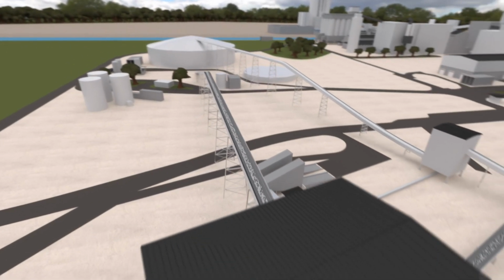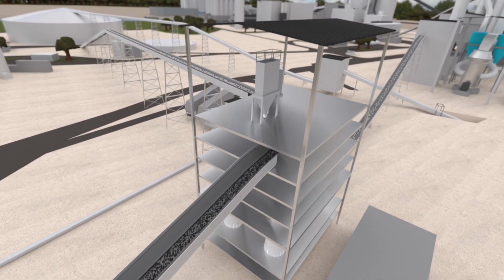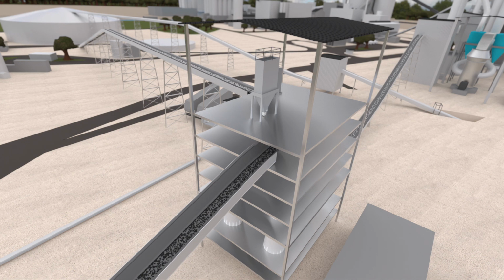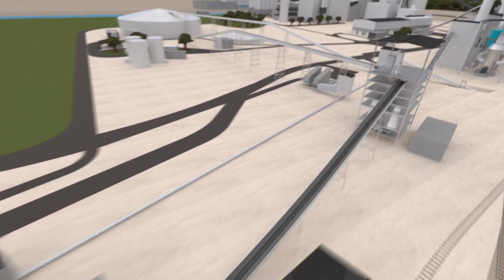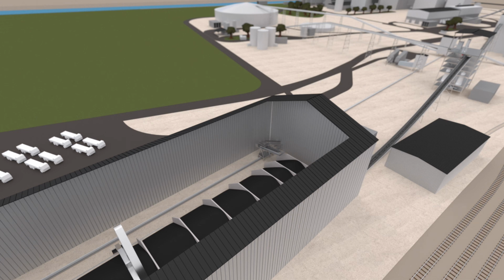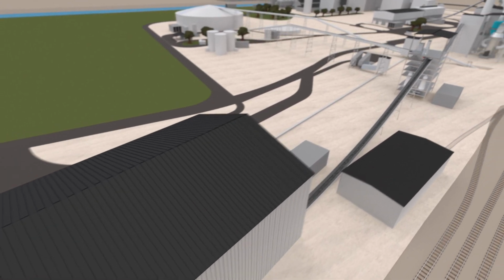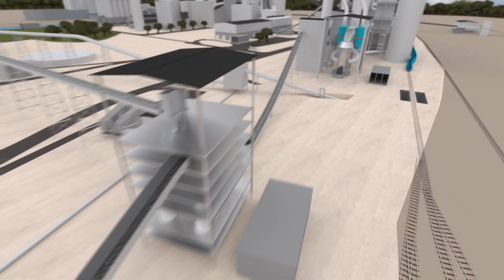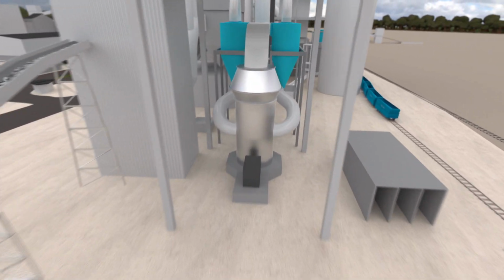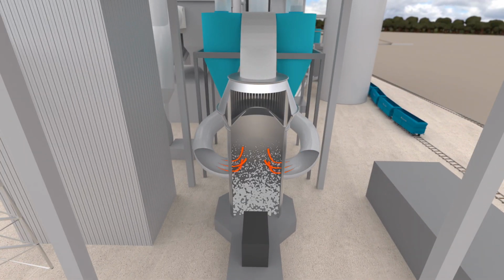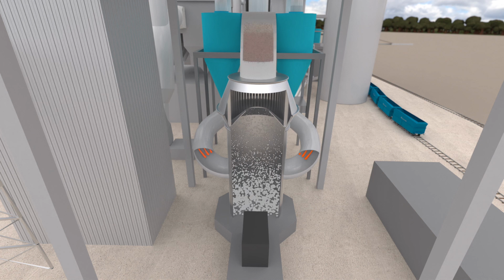The limestone taken from the hall is sent to a dosing unit. In this unit, corrective materials are added, as well as alternative raw materials in order to save on natural resources. Each carefully measured constituent is ground in the vertical roller mill and dried by hot gases recovered from the kiln. At the exit of the mill, we obtain a very fine powder called raw meal.